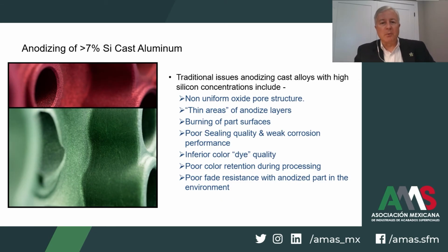Traditionally, these examples in the list as shown are many reasons why cast alloys have been avoided for processing through sulfuric anodizing processes. Poor dye quality, poor color retention, burning of parts have always been a problem. It's actually the high silicon that causes the anodizing to have these tendencies for burning or low thickness spots that cause coating performance issues. So the ability to overcome the impact of the silicon in creating a thicker anodized oxide was the target for success.